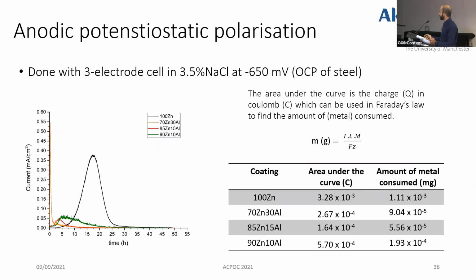I also did this electrochemical test, which is anodic potentiostatic polarization, and it was done also with the 3 electrode cell setup in 3.5 percent NaCl at the OCP of the steel. And this is done to see 2 things. The first one is to calculate the amount of metal dissolved or consumed in this time, and also to see how the current is passing and what the period of current passing is in these coatings. So you can see the broader or the higher the area under the curve, the more the zinc or the more the metals are dissolving in the coating.